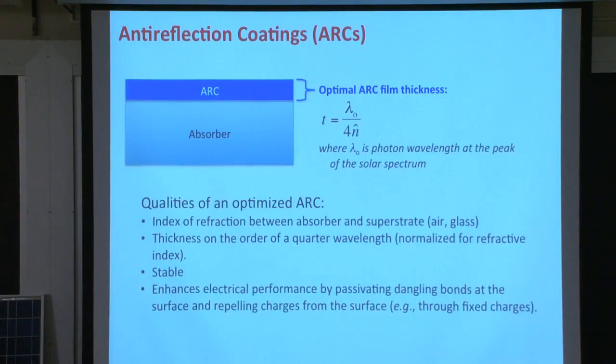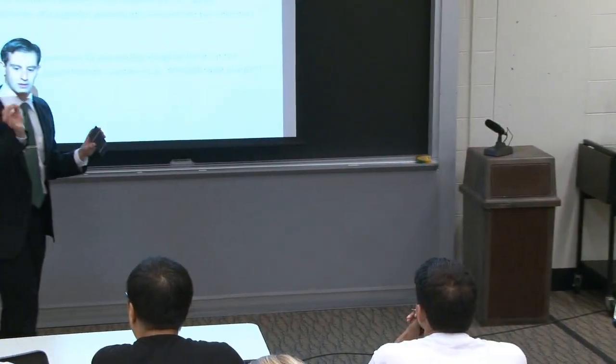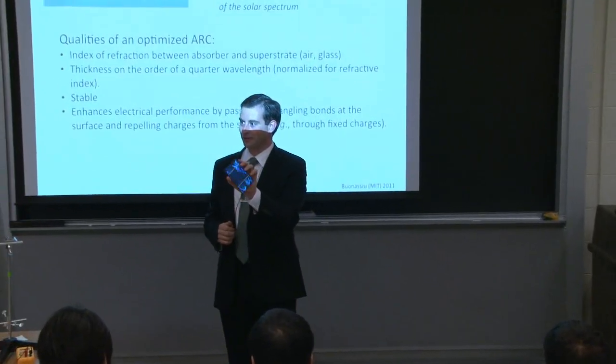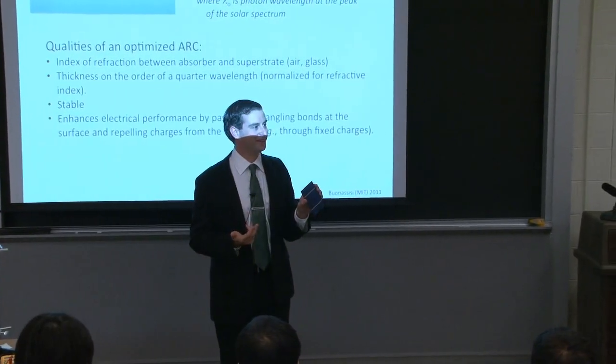So what thicknesses are folks coming up with? Order of magnitude? 70 nanometers. 70 nanometers. That's almost spot on to the actual thickness, which is somewhere on the order of between 70 to 80 nanometers typically. You're telling me that something that is 1/1000th the thickness of my hair is deposited on the surface of this wafer and is absorbing all this light?